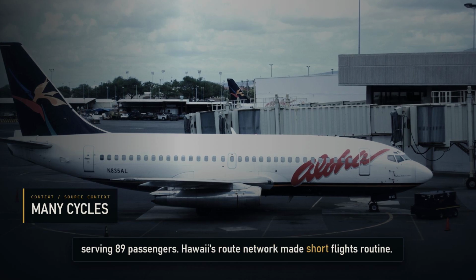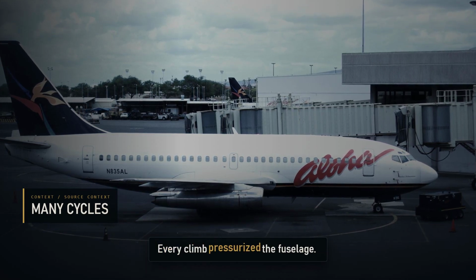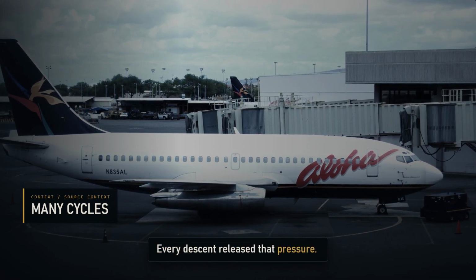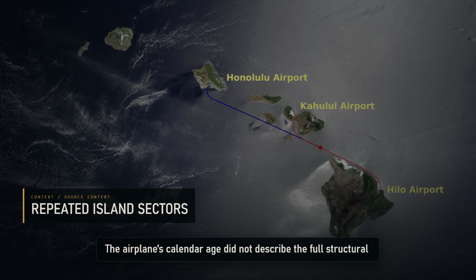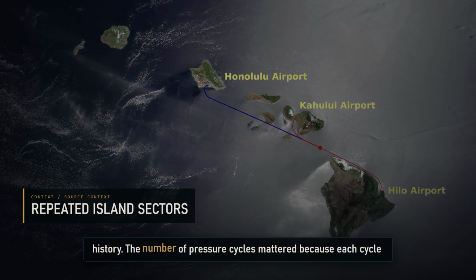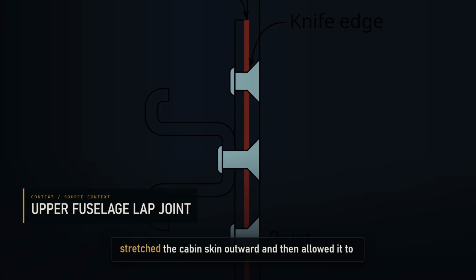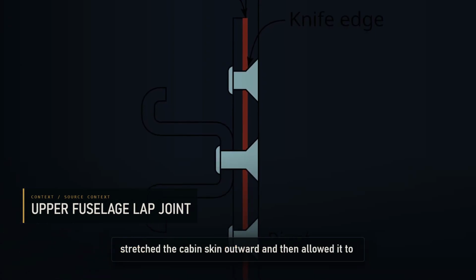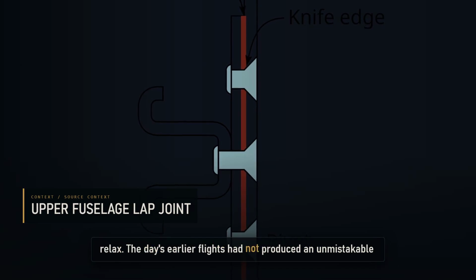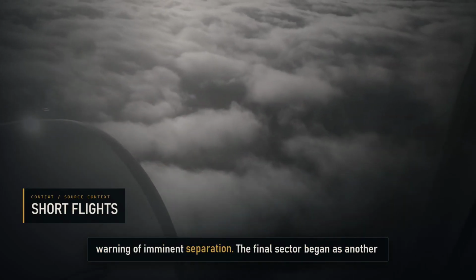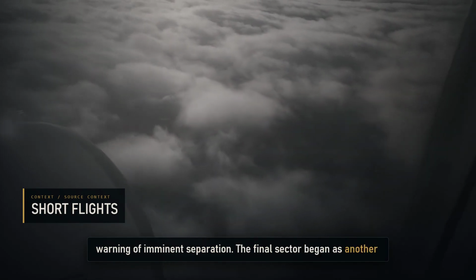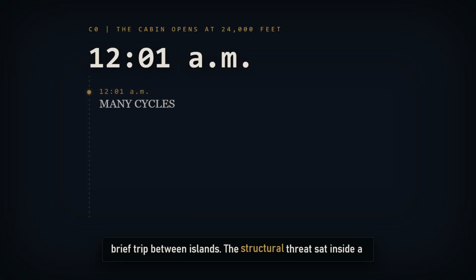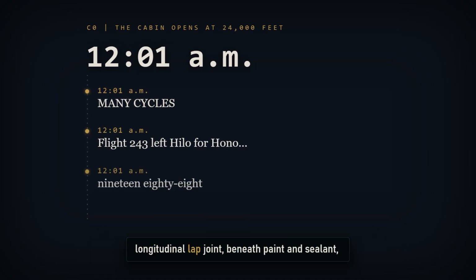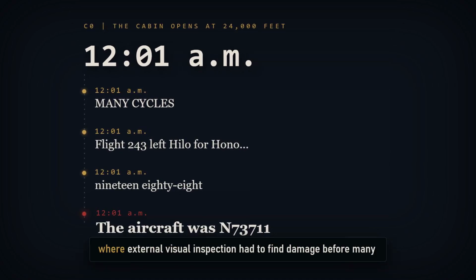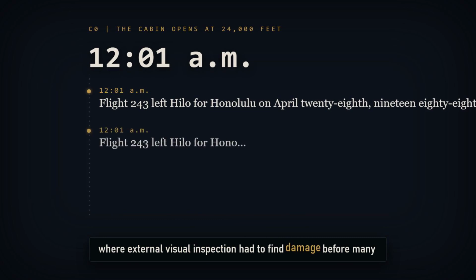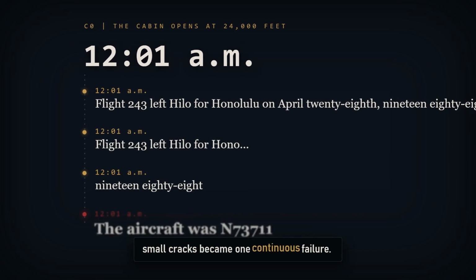Hawaii's route network made short flights routine. Every climb pressurized the fuselage. Every descent released that pressure. The airplane's calendar age did not describe the full structural history. The number of pressure cycles mattered because each cycle stretched the cabin skin outward and then allowed it to relax. The day's earlier flights had not produced an unmistakable warning of imminent separation. The final sector began as another brief trip between islands. The structural threat sat inside a longitudinal lap joint, beneath paint and sealant, where external visual inspection had to find damage before many small cracks became one continuous failure.